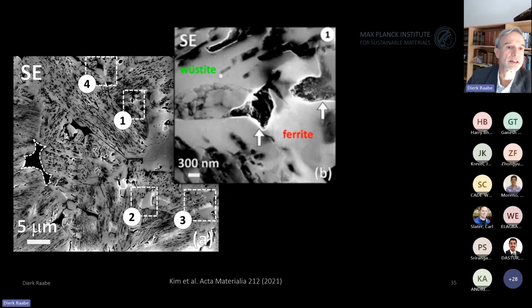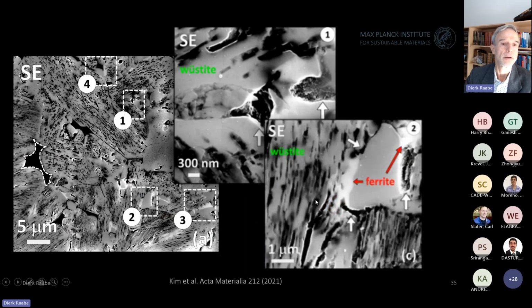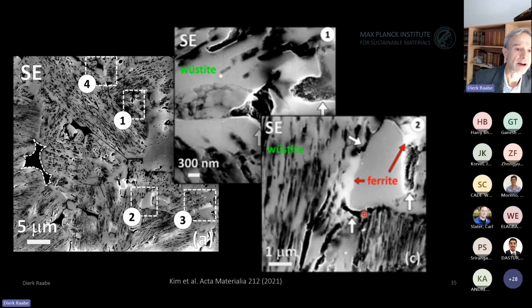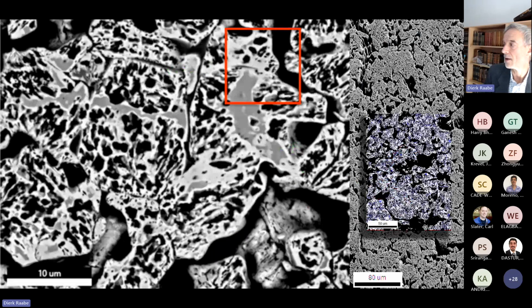Here, for instance, you can see that in some areas, indeed, the wüstite is, as I said, surrounded by very dense layers of ferrite. But you can also see in this diagram that you have delamination, maybe enhanced also by hydrogen, that we don't know, where you then, like here and here and here, create also new fresh surfaces where the reduction can go on. That means it's also from the defect, damage, and transport side a very heterogeneous scenario where the porosity does not only come from the mass loss, but also from damage and fracture.